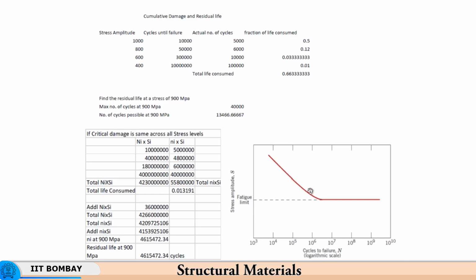So, the stress at which the workpiece can withstand 10 to the power 7 cycles without any kind of failure is given as the endurance strength. So, you can be sure that the material will endure that much stress forever. So, the crack will not propagate, the defects inside will not grow into cracks, and they will not result in any kind of fracture, and so the fatigue life can be taken as infinite, because the defects would remain inside without getting enlarged any further. So, that brings us to another issue which is again related with crack propagation and so on.